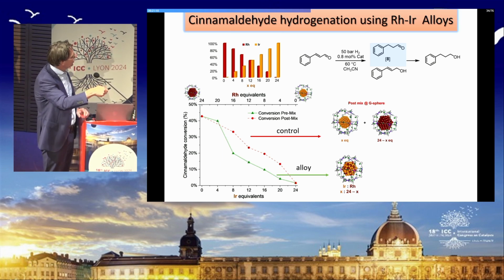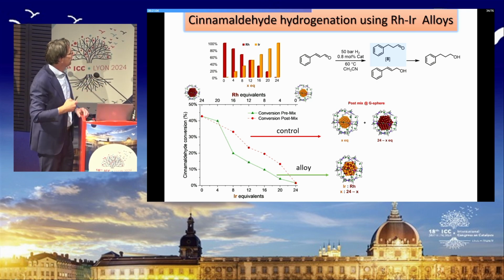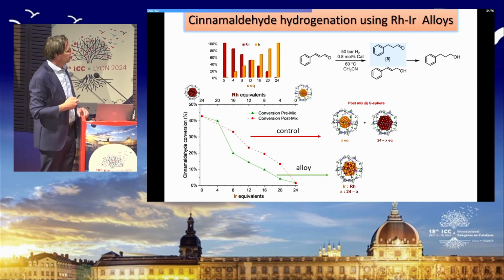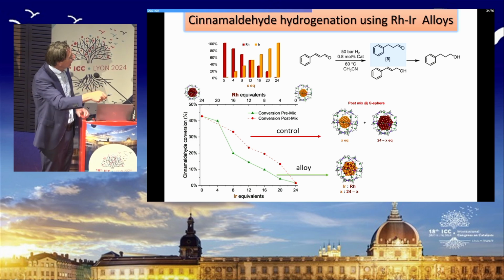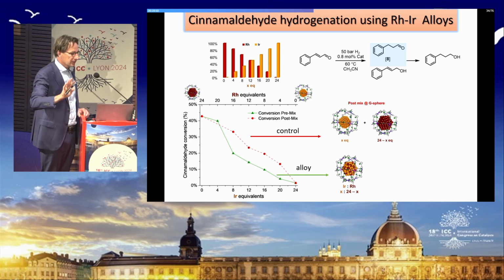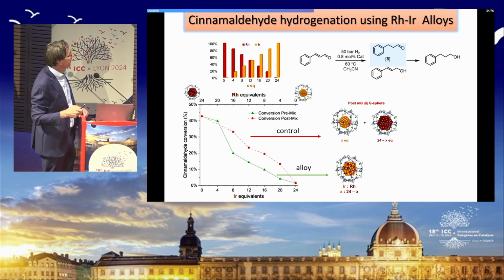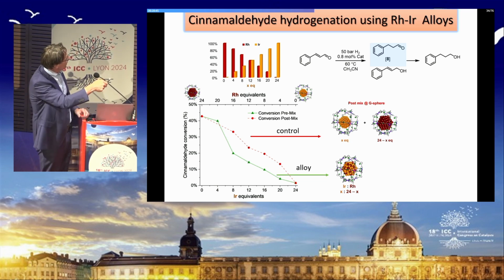And here we see two different experiments where we vary the iridium content, and we see the conversion of cinnamyl aldehyde after 2 hours of reaction using the alloy, and using in the control a mixture of pre-prepared pure iridium with pure rhodium. So this is the pure iridium, pure rhodium, which is more or less a linear line as expected. And here you see deviation.